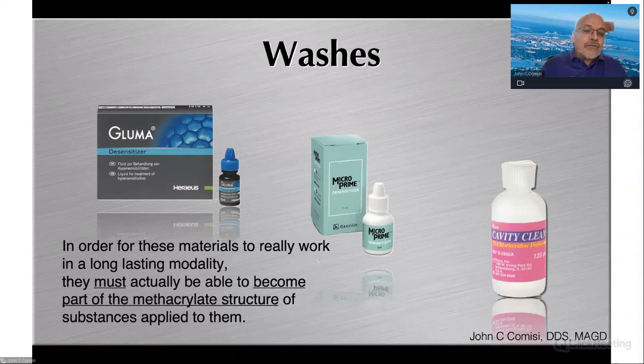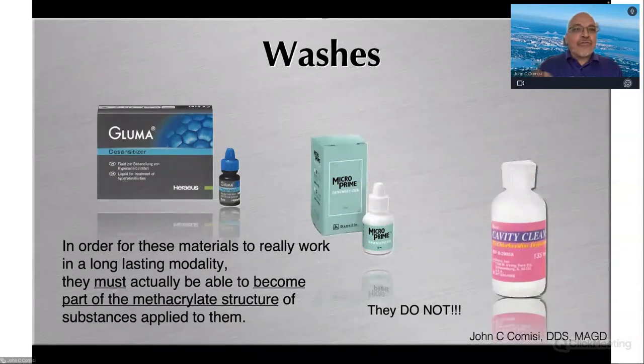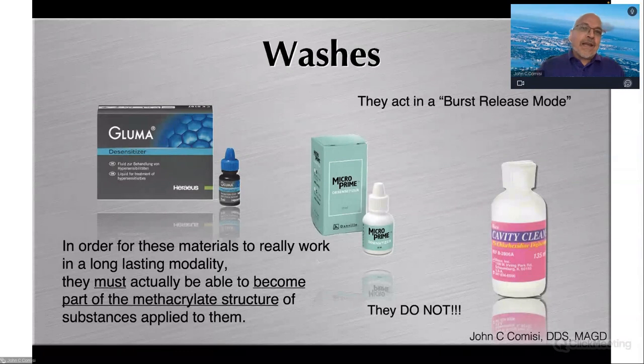And interestingly enough, in order for these materials to really work in a long-lasting modality, they must become part of the methacrylate structure of the substances that we apply to them. But unfortunately, they do not. They are not methacrylate-based. But John, methacrylates are problematic in whatever we do. Yes, but if we're going to use these items to be antimicrobial and we're going to try to bond to them, how is that happening? And also, they work in a burst release mode. That means as soon as you apply them, a lot of it dissipates into the oral cavity, and after a period of time is no longer present and available at a later time period when most of our restorations fail.